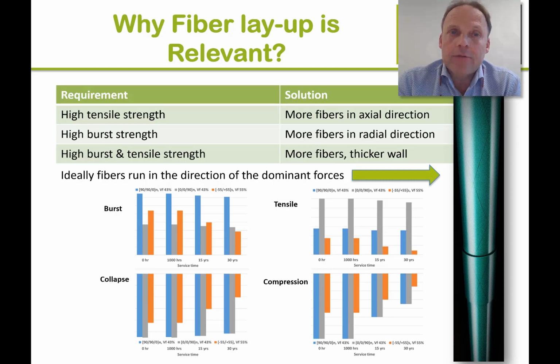Now ideally you would have the fibers run in the direction of the dominant forces. Dominant forces downhole are typically in the axial direction and in the radial direction. If I can please take you to the slides that you see below. They have 3 bars. The blue one is for a composite structure like Akit can make, where the fibers run in the 0 and 90 direction. So all the fibers run in the axial direction or in the radial direction. And in fact, there's twice as many in the radial direction as the axial direction. A lot of fiber in the radial direction means a high burst resistance.